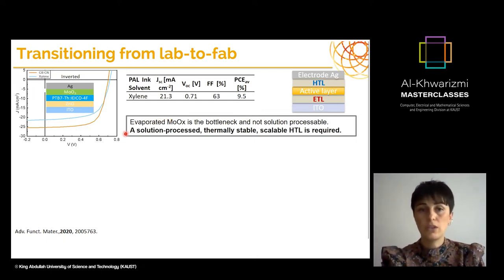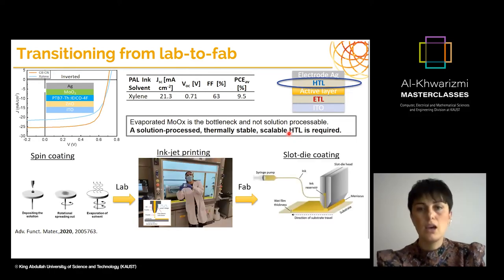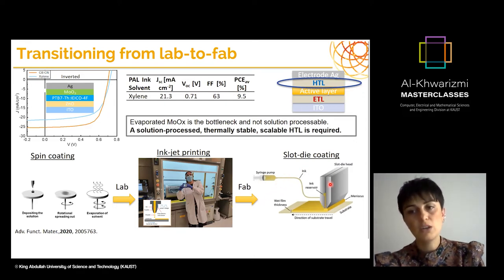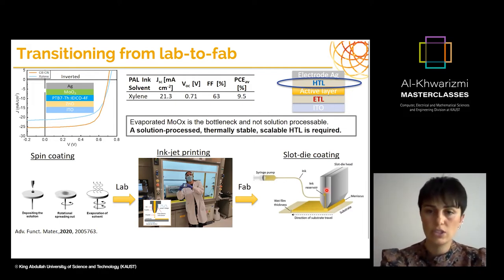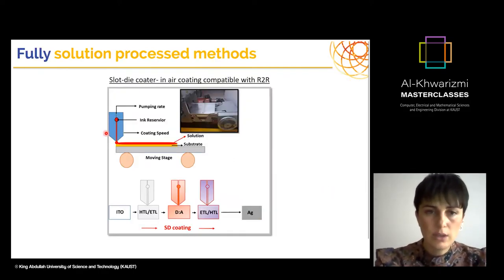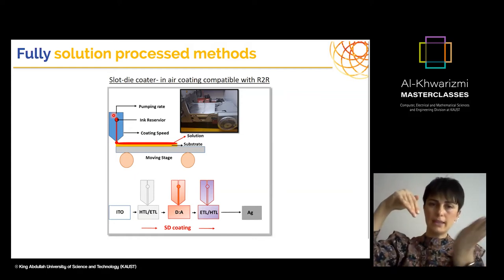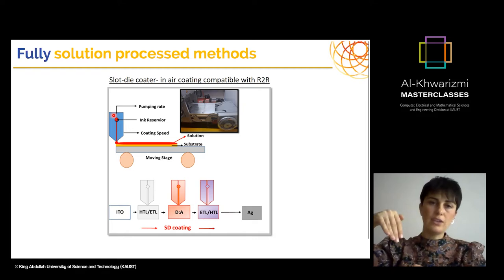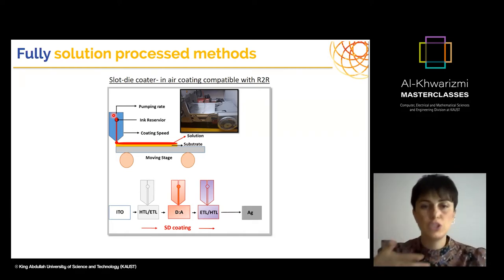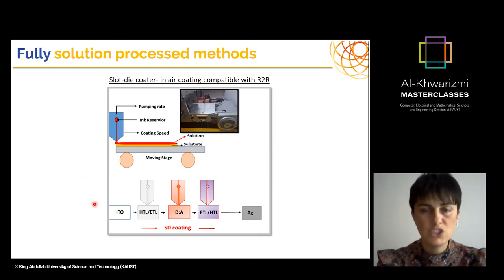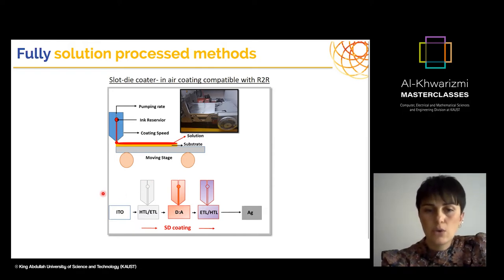So then we started to think we definitely need a solution processed, obviously thermally stable and also scalable hole transport layer. That transport layer is actually going to sit on the photoactive layer, if you realize. And for this reason, we moved from spin coating methodology for every layer and moved instead to inkjet printing and also another coating technique called slot die coating, which is compatible with roll-to-roll coating as in this technology to scale up. So the slot die coating can offer two different mechanisms here. Either the head can be stable and the stage is moving, or the other way around. You can have a stable stage and the head can move if you want to do sheet to sheet production. And as I said, we did inkjet printing for all the layers, and also we wanted to compare the slot die coating with every single layer.